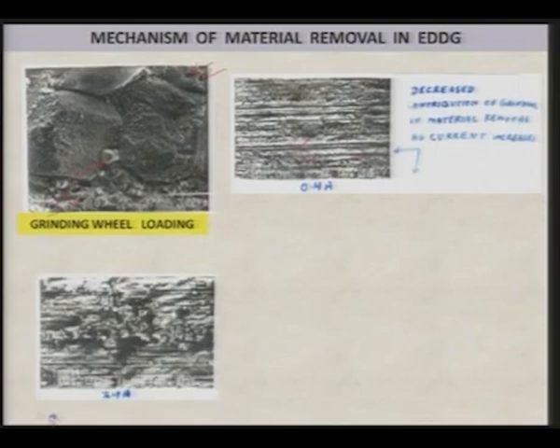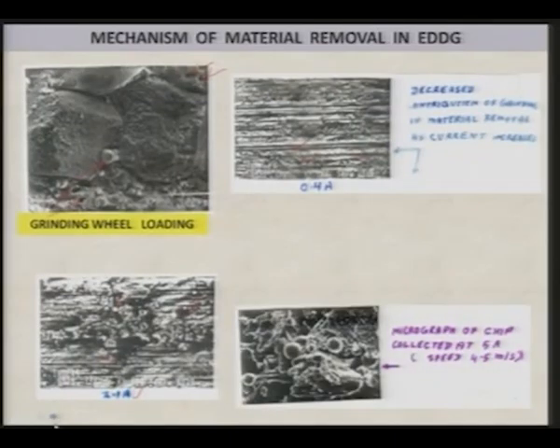Now, at higher current, that is 2.1 ampere, you can clearly see the crater formation, the removal of the material by the craters. If you see this particular point here, it looks like a globule, and this globule indicates that material is being removed by melting phenomena as well, because when material gets melted out and solidifies, its shape is spherical, and that is what you can see here. It will be more clear in this particular picture.